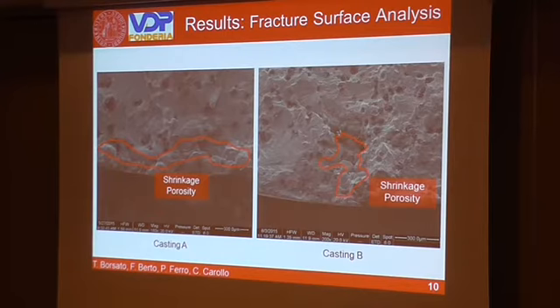Fracture surfaces were evaluated using a scanning electron microscope, in order to evaluate the crack initiation site. For all the specimens, shrinkage porosities act as crack initiation sites, and it can be seen in these figures that for casting A, the shrinkage porosities are greater than in casting B.